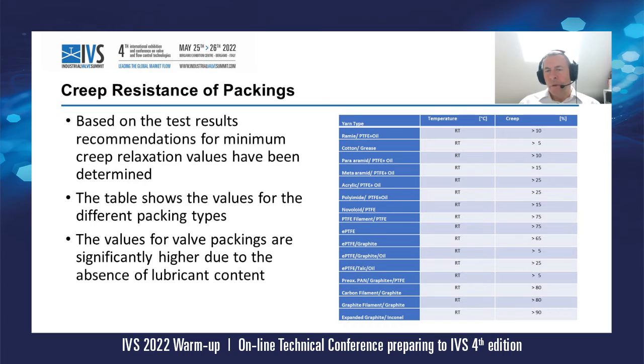You see the difference here in the creep values for the typical pump packings which contain a grease or lubricant as a running-in lubricant. These values are quite low because again the oil will run out under pressure, which is intended for pump packings to counteract the heat dissipation. For the valve packings we have significantly higher values, which really starts for PTFE with creep values bigger than 75, or for carbon filament values bigger than 80%, and with expanded graphite reinforced with Inconel we have values that are even bigger than 90%.